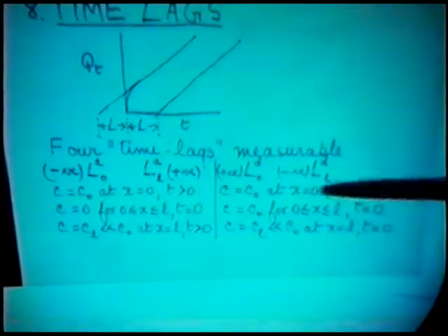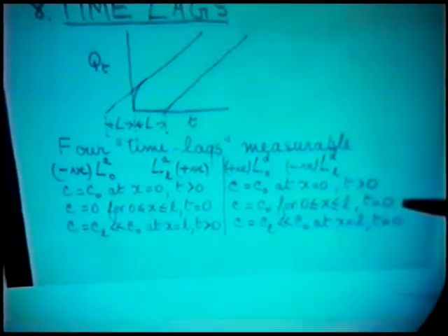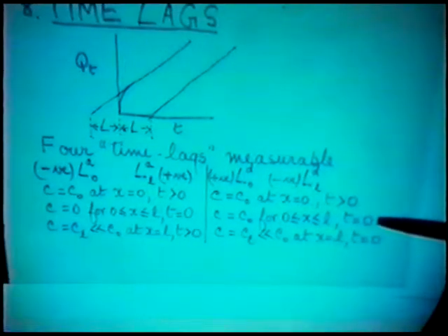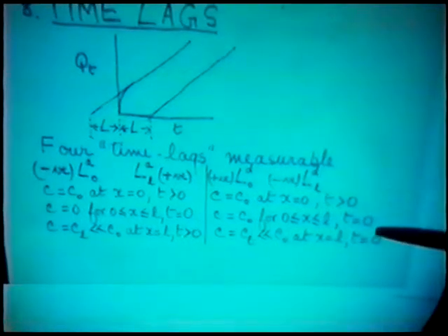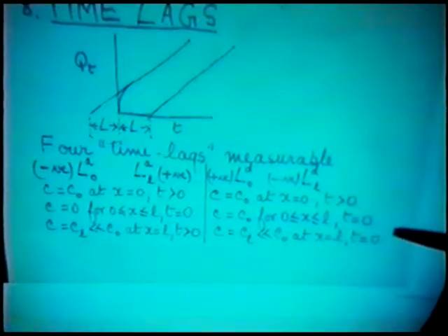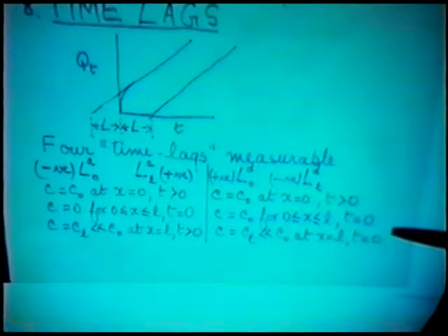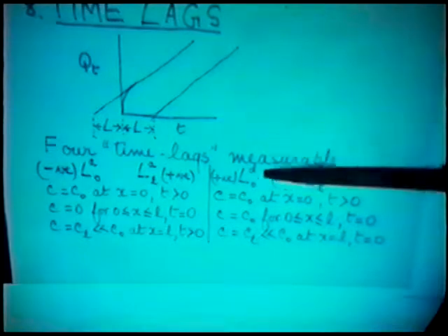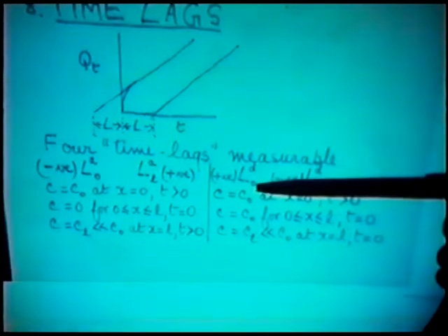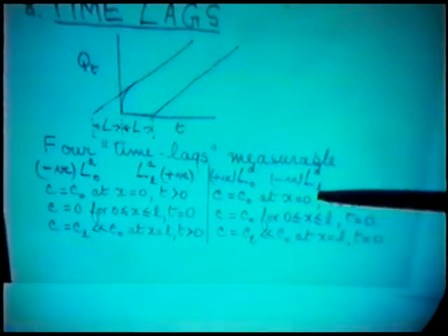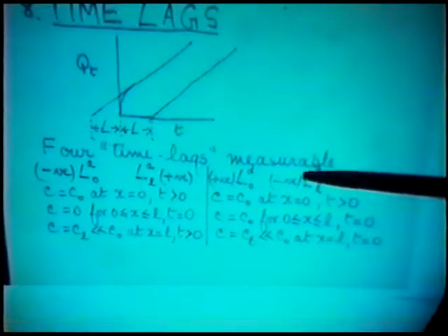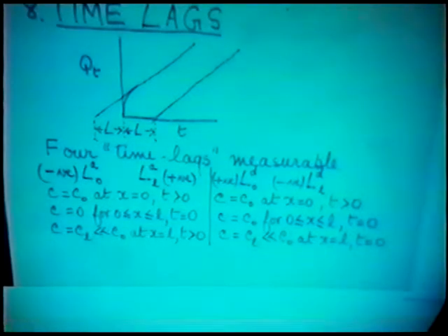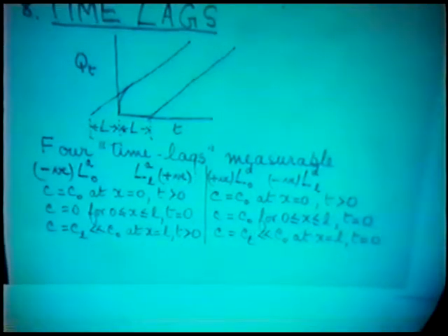Then you can also have the membrane containing a uniform concentration of sorbate, and you allow it to empty itself down to a steady state condition. Now we have 2 desorption time lags, and that at the ingoing face is positive, and that at the outgoing face is negative in this case. Each of these, as I've said, is accessible directly to experiment.